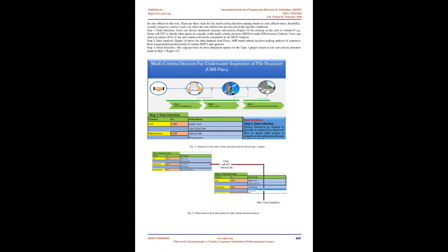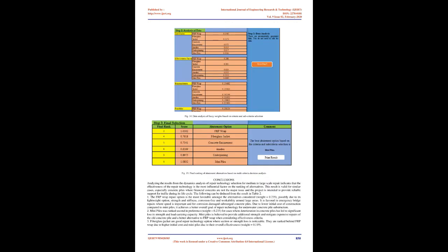Dynamic sensitivity analysis. A dynamic sensitivity and performance analysis were carried out to examine the performance of repair technology alternatives, considering the overall objective of selecting a repair technology for a moderately damaged underwater pile. As shown in Figure 8, FRP wraps have an overall highest weight performance, 0.239, followed by mini piles, 0.237, and fiberglass jacket, 0.125. The use of epoxy, 0.07, high-strength mortar,